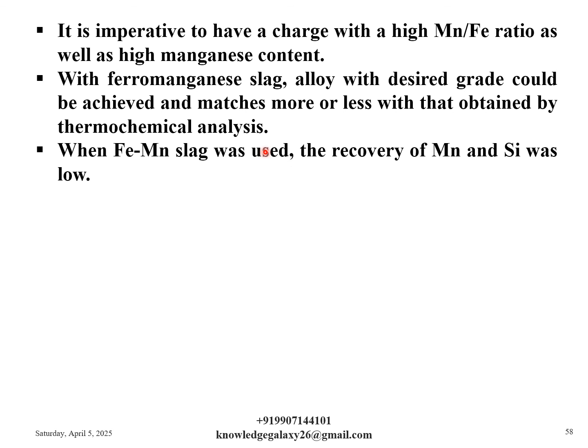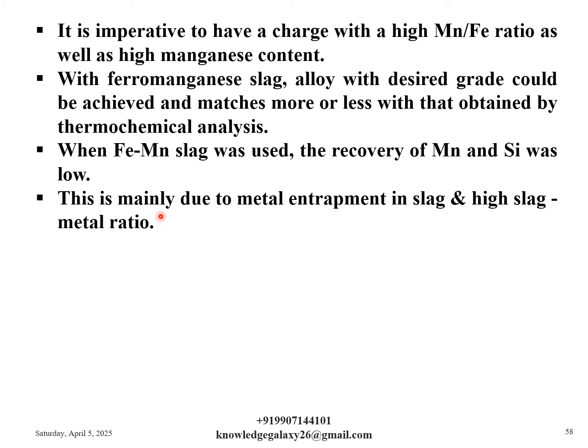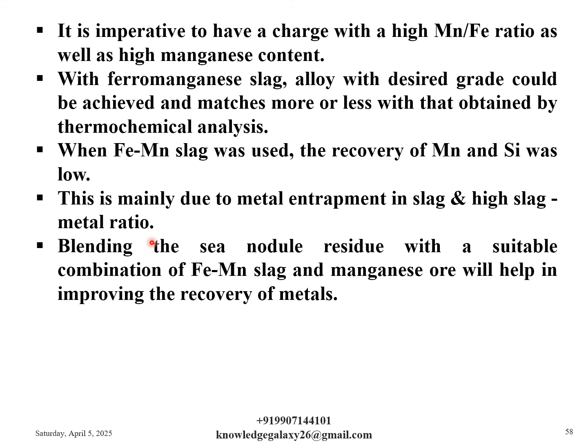When ferromanganese slag was used, the recovery of manganese and silicon was low. This is mainly due to metal entrapment in slag and high slag by metal ratio. Blending the sea nodule residue with a suitable combination of ferromanganese slag and manganese ore will help in improving the recovery of metals.